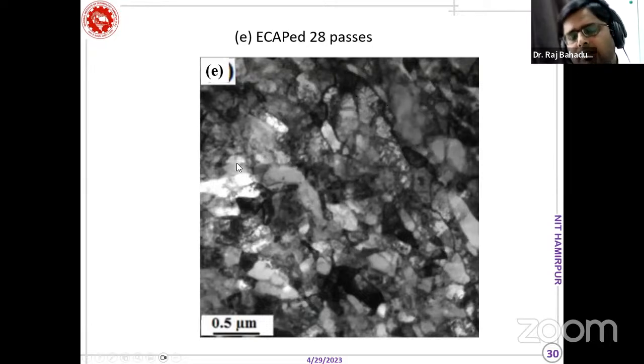Then you will find almost equiaxed grains are forming, of the dimension basically 0.2 to 0.3 micron. And we have also calculated the dislocation density. So dislocation density is also very high. So we have refined the grain size. We have introduced more and more dislocations. So this is the good recipe to increase the strength of the material.